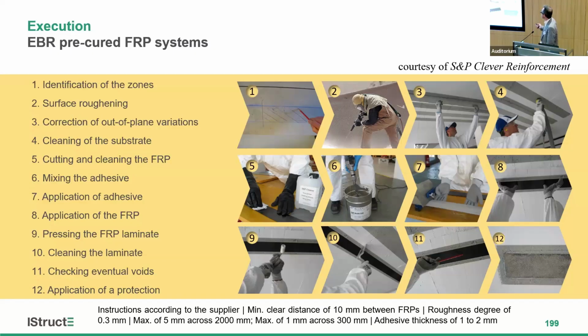Then we have to clean the surface, also clean the reinforcing material, prepare the adhesive according to the supplier instructions, and apply the adhesive on the surface of the element. And since these materials are really light, you can see that they can be easily handled by hand without any lift to apply them. Then, of course, you have to press in order to have the adhesive flow to the lateral faces, clean the laminates, and finally, after curing, you have to check if there are eventual voids, and if needed, you can also add additional protections.